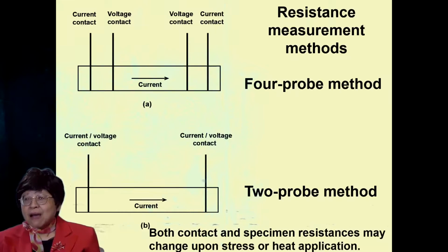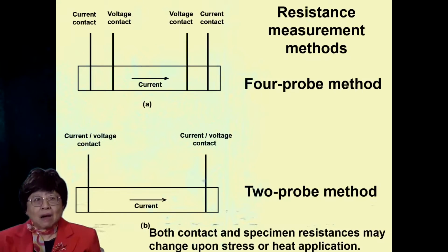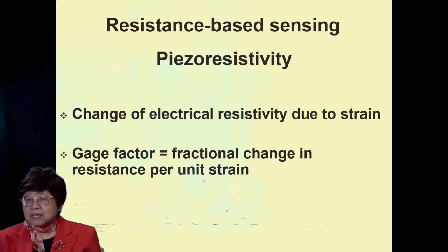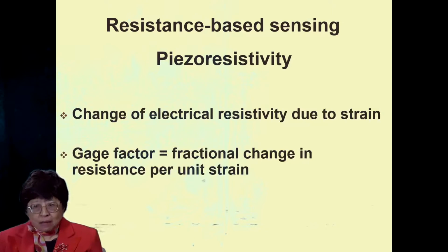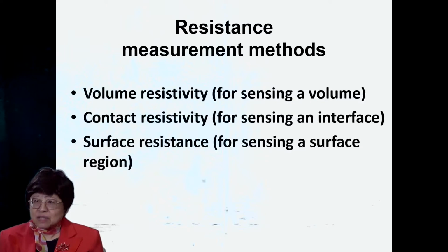And if one is trying to find out the effect of stress or heat on the resistance, it'd be even more troublesome for the two-probe method because both the contact resistance and the specimen resistance may change at the same time. Resistance-based sensing is largely based on piezoresistivity, which refers to the change of the electrical resistivity due to the strain. The severity of this effect is called the gauge factor, which is the fractional change in resistance per unit strain. There are three styles of resistance measurement: volume resistivity for sensing a volume, contact resistivity for sensing an interface, and surface resistance for sensing a surface region.